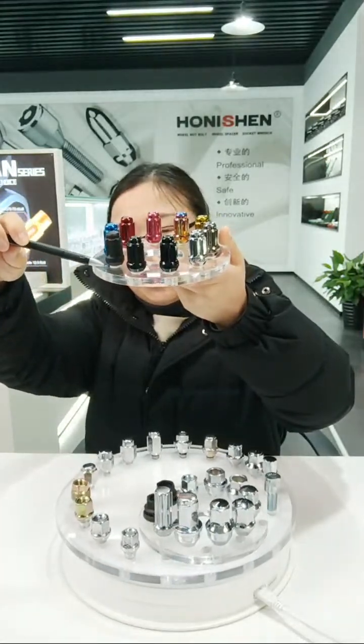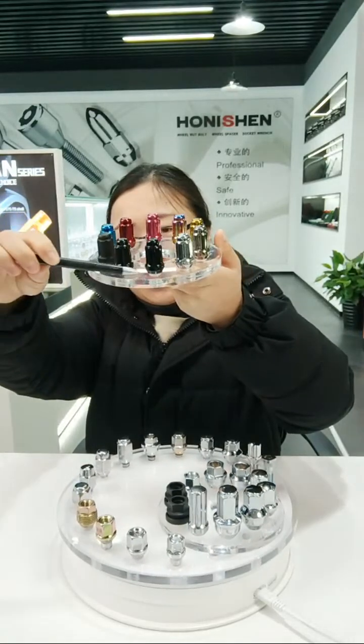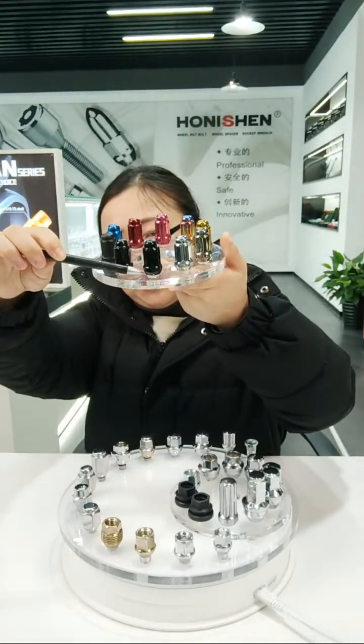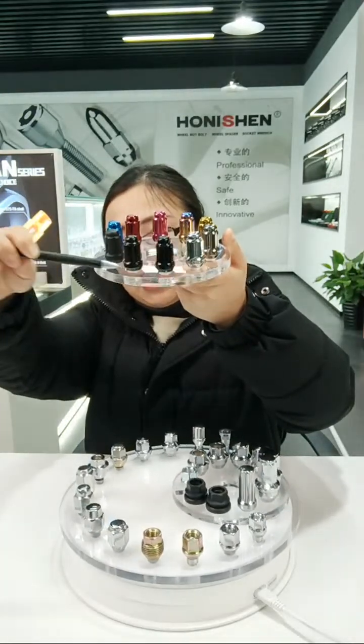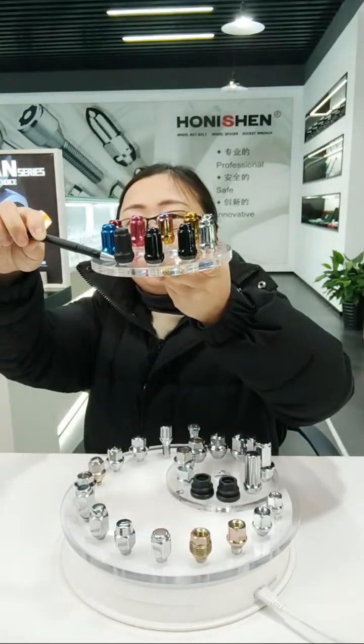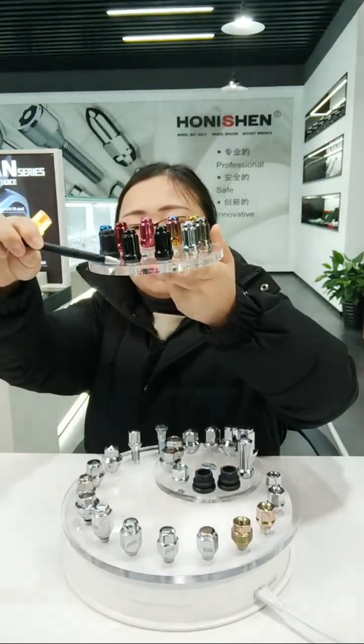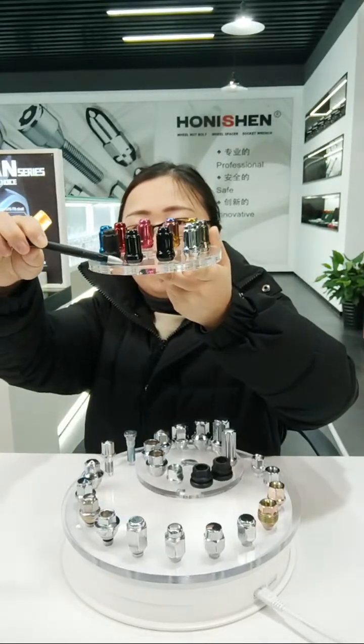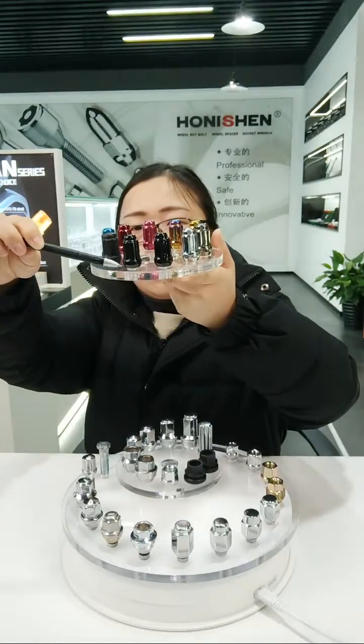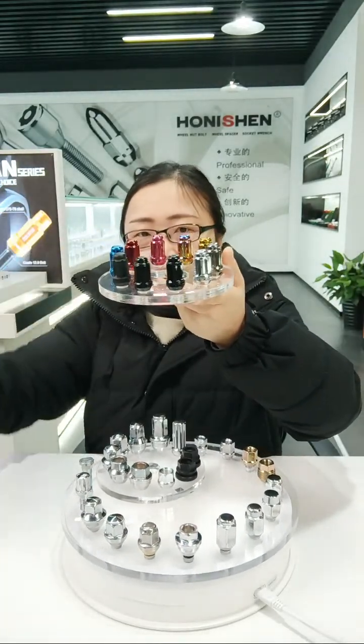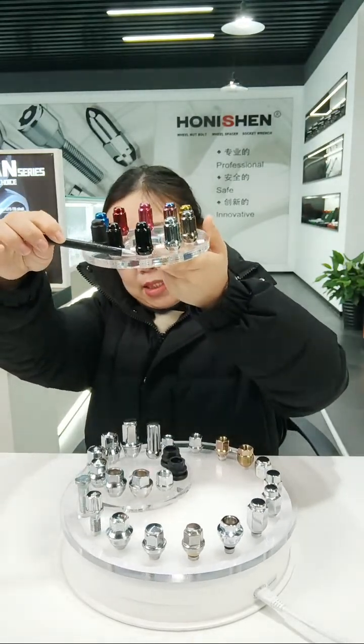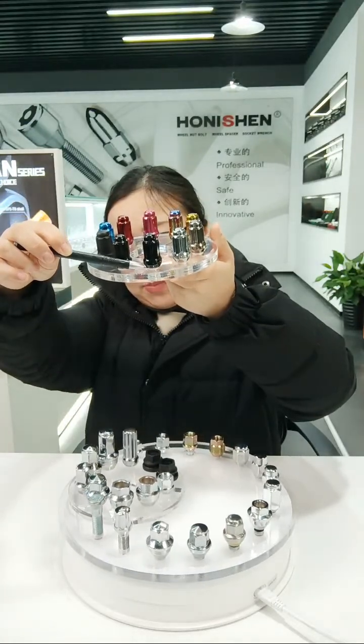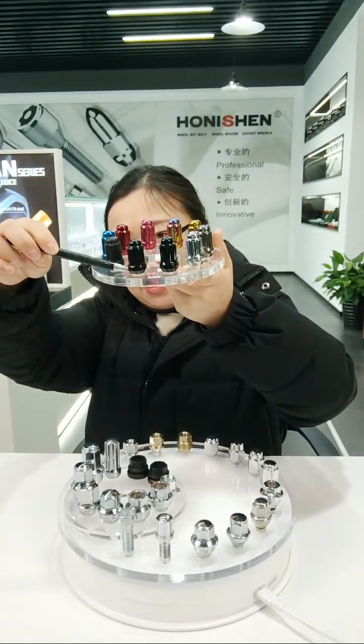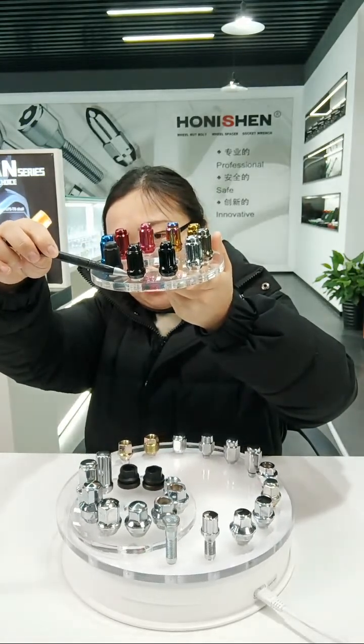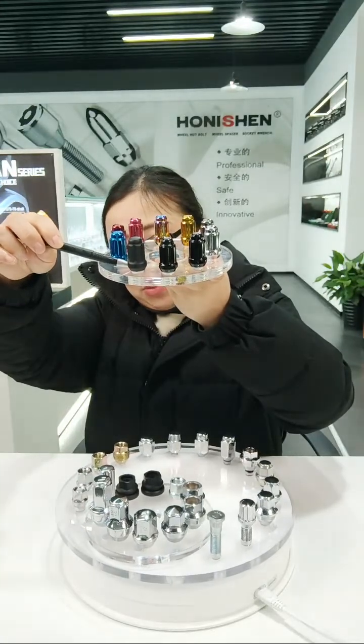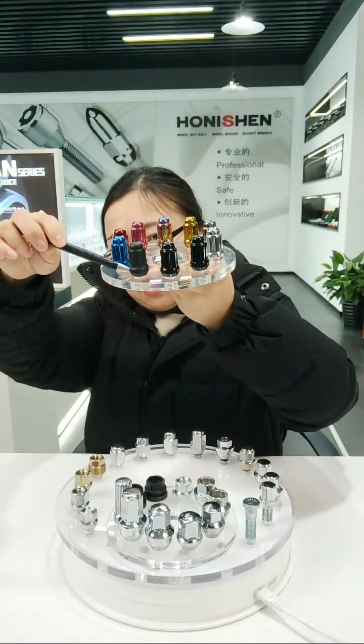Do you know the difference between them? You see, firstly, the color brightness is different. This is bright white. This is matte black. And the color fastness is different. Matte black is the best. Also, the natural salt spray test is different. The black zinc could pass 96 hours natural salt spray test. The black electrophoretic only can pass 48 hours natural salt spray test. The matte black could pass 200 hours for natural salt spray test.